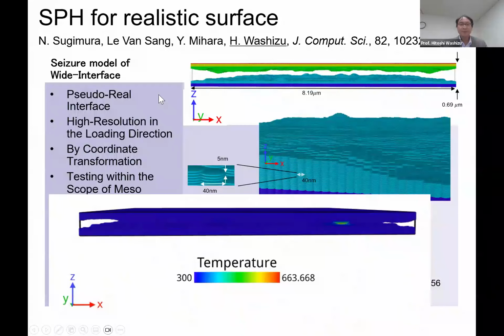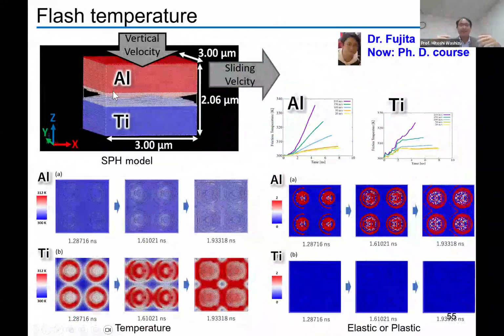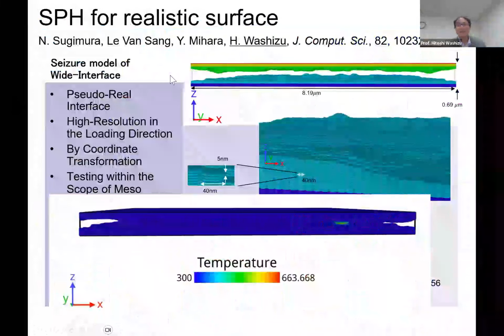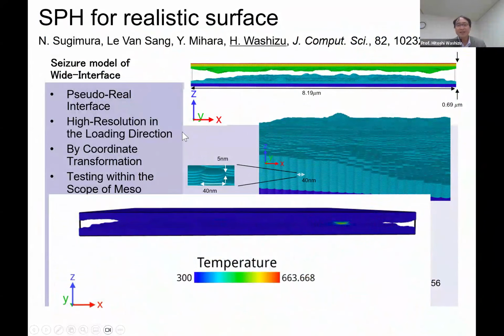But this kind of surface roughness is very artificial, and a realistic system is like this, and we extended this. And one more thing is that we made some sphere particle into a coin-like particle. Using the coin-like particle, lubrication occurs in this kind of anisotropic system. It means that in the sliding direction, it is much larger, but in this side, it's not.